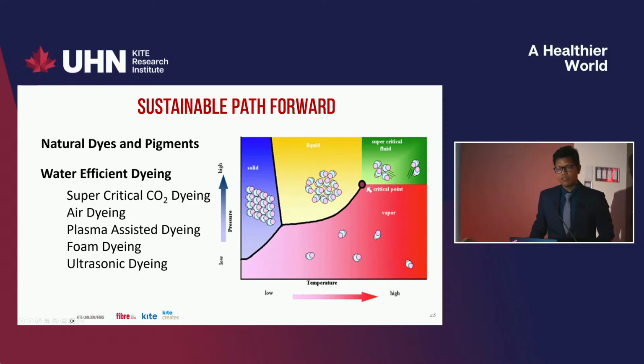And there are some water efficient dyeing processes as well. The one example I'm showing here is supercritical carbon dioxide dyeing with high pressure and temperature. The carbon dioxide goes above a critical point, and with that, we try to disperse the dye inside the fiber material. There are also some other dyeing processes: air dyeing, plasma assisted, foam, and ultrasonic. For supercritical carbon dioxide dyeing, you don't need to use any water, and 95% of the supercritical carbon dioxide you can reuse or recover from the chamber.